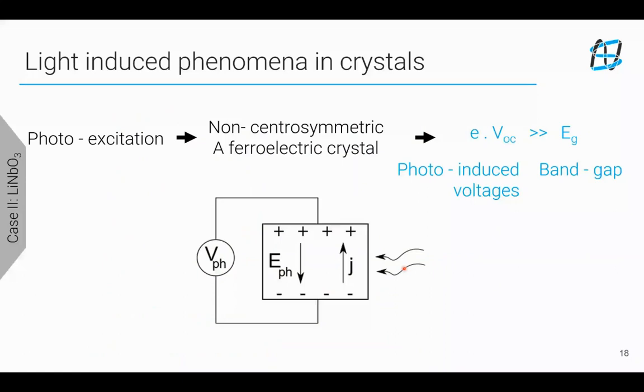Now, usually in silicon, the open circuit voltage generated from silicon-based solar cells is lesser than the band gap, so it never exceeds the band gap. But it is fantastic that in these ferroelectric non-symmetric crystals, this is enabled. This kind of phenomenon is called the bulk photovoltaic effect.